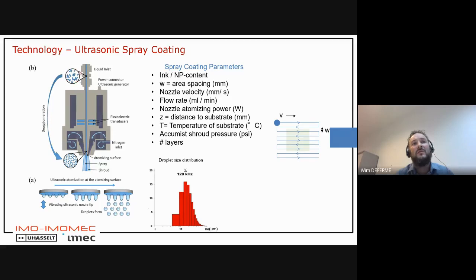So you have your liquid here, your ink here, functional ink. And, of course, the chances are there that in this functional ink, some nanoparticles will cluster together. And if you look in research, people try to use ligands and these kinds of things to stabilize these nanoparticles, not to cluster, not to agglomerate together. But what we saw in using this ultrasonic spray coater is that also by using ultrasound, you get, let's say, a homogeneous distribution of your nanoparticles, for example, or your polymer inside your liquid, and finally also in your droplet.